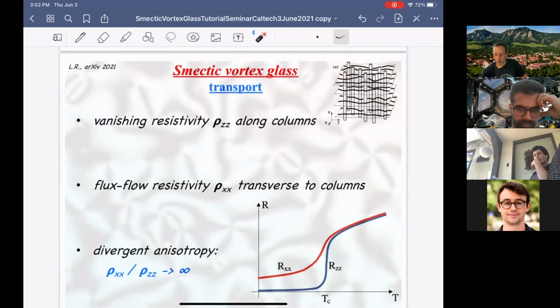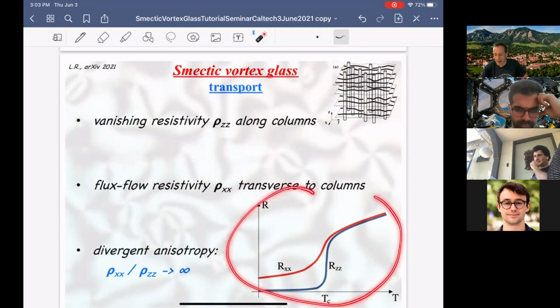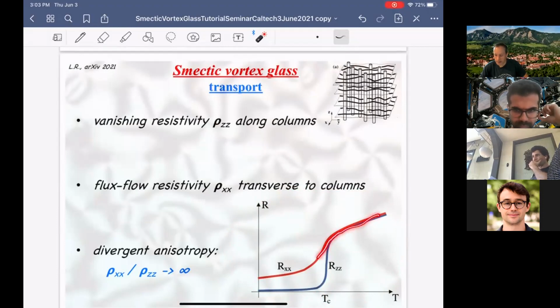On the other hand, if you try to flow current perpendicular to this direction, then there's a force on vortices along columns. But since there's no pinning along the columns, the whole structure can just slide, and there's a flux flow resistivity for current along the x direction. So this results in a divergent anisotropy in the resistivity. Schematically indicated here, below T_c, rho_zz goes to 0, while rho_xx is finite at any finite temperature.